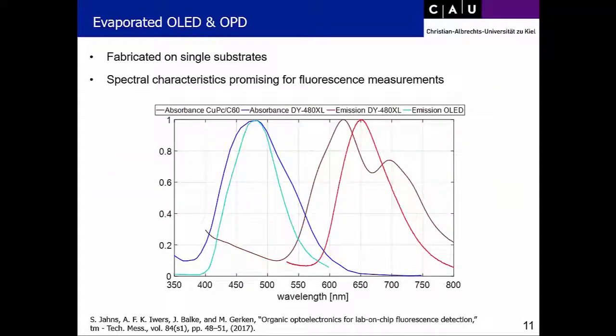And this is what the spectral characteristics are. So we have the emission of the OLED in the light blue, that's this curve here. We have the absorbance of the fluorescence dye we matched it to, shown in dark blue here. We also have here in red the emission of the dye that we selected, and in brown, that is this curve here, we have the sensitivity of the OPD in this system.